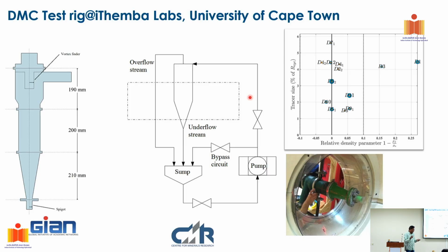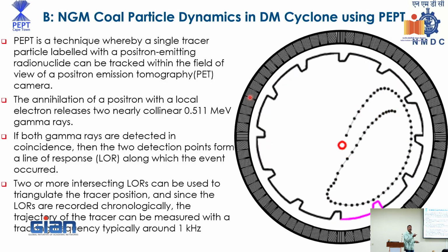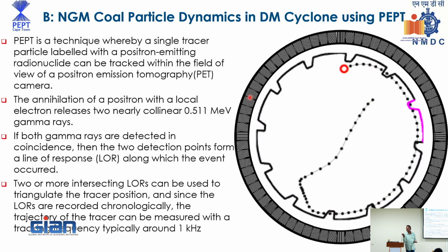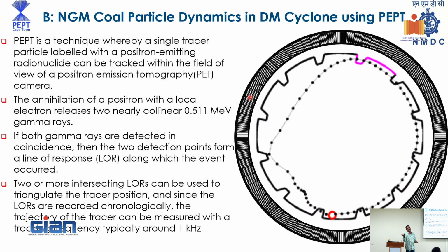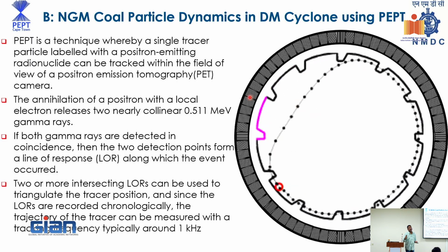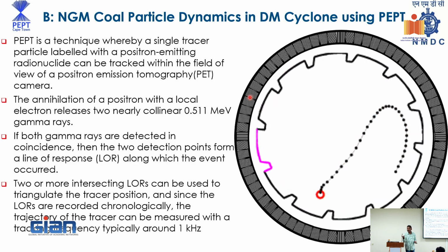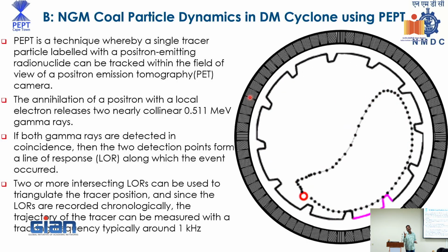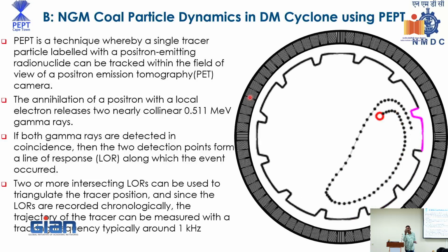So now with that, in the previous slide, you can determine location and the time. Once you know the spatial coordinates and the time, if you differentiate it, you get a velocity. If you go for double differentiation, you get an acceleration. So if you know the position, velocities and acceleration, you can calculate the forces that are acting on the particle.